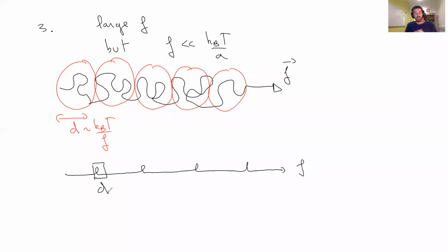But what is interesting is that before we were dealing with dilute solutions and then semi-dilute solutions. When you deal with semi-dilute solutions, you have average crossing between the chains in the solution, which naturally defines psi, the size of a blob. Now I have only one single chain, but I have a force that pulls on it. And this force, compared to kBT, provides me a typical length scale that defines a blob. Again, a blob is defined the same way as before. Inside it, it's an unperturbed feature; it will do its Flory-like behavior. But above that, you have a linear assembly of objects. So the force is dominating. It's really aligning the blobs in a linear assembly.